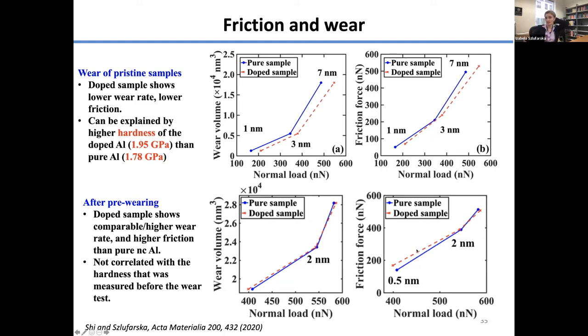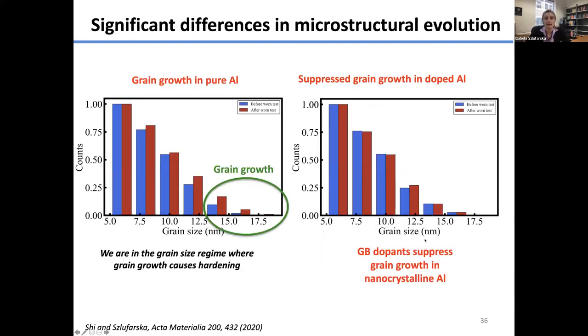So why is that? What happened? It turns out that, as we expected, in the pure nanocrystalline aluminum we had a pronounced grain growth. But in the doped samples, the grain size was quite stable. We saw no grain growth on the time scales of our simulation. So the trends are shown here. This is basically a histogram of the grain sizes in nanocrystalline aluminum. Blue is before sliding, red is after sliding, before pre-wearing and after pre-wearing multiple times. And when we really induce the microstructural evolution, you can see the appearance of new large grains. And that does not happen when you have dopants present in the samples. So this is the main point, that the zirconium dopants here suppressed the grain growth of nanocrystalline aluminum.